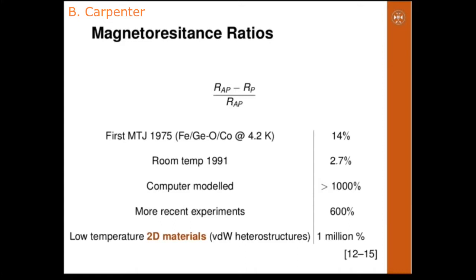A computational bit is represented ideally by a zero resistance on state or an ideally infinite resistance off state, and so the difference in resistances between aligned and anti-aligned states of a magnetic tunnel junction should be high. The original discovery for tunneling magnetoresistance found only a small percentage difference in the on versus off state current. This is quantified via a magnetoresistance ratio, defined as the difference in resistances of the parallel and anti-parallel cases divided by the larger resistance anti-parallel case. Basically, higher ratio, greater difference in the on versus off current through the device, and so a better device.